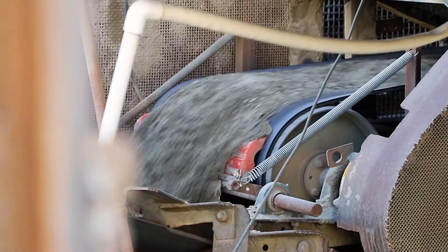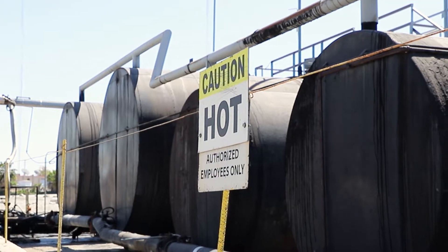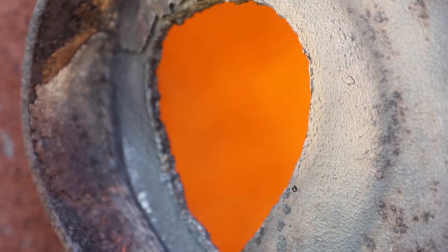What is asphalt? Asphalt consists mainly 95% aggregate and around 5% polymer grade asphalt cement oil. The aggregate is heated to over 500 degrees, then introduced to the oil in the pug mill and mixed for approximately 35 seconds.